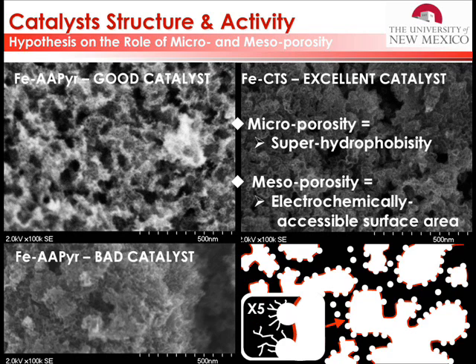Practically speaking, these are different catalysts that we have produced. Again, I apologize for the projector, but you can see the difference between a good catalyst and a bad catalyst. The bad catalyst from the same chemical family has much finer morphology, and it became super hydrophobic, so you cannot wet it. The good catalyst is just below the level of super hydrophobicity. You can wet it. At the end of the day, if your surface area, for whatever technical reason, goes above 400 to 600 square meters per gram, you are not adding to the reaction. You need to keep your surface area below a certain threshold to be accessed by the water.